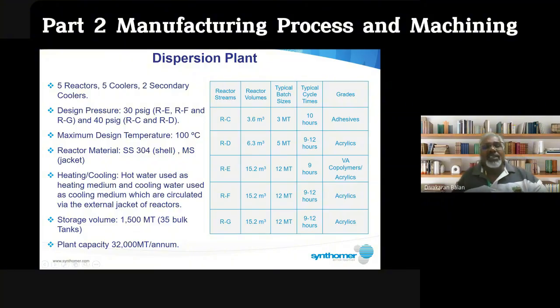These 5 reactors, we call them with alphabets from C to G. So you can see RE is reactor E, RF is reactor F. And here is reactor G, this is reactor C, and reactor D. So it's from C to G. Why C to G? Because we used to have A and B, very small reactors at a different location in Kluang, but they're already decommissioned, there's no more. So that's why the remaining is C to G, 5 reactors. So far okay? Am I clear?